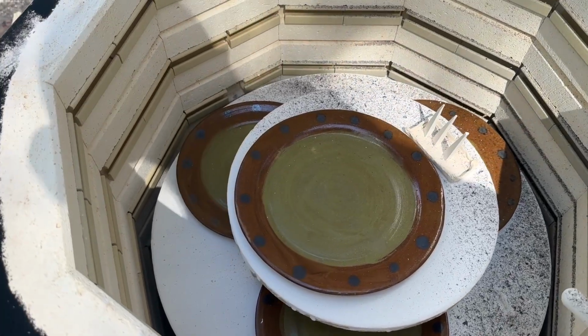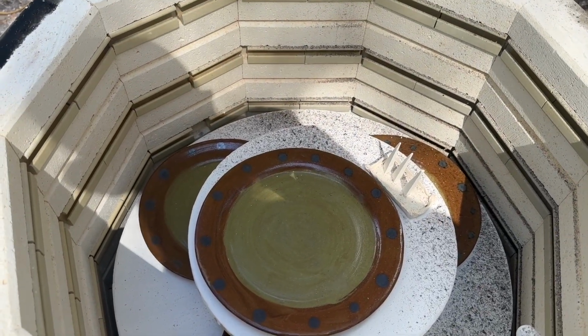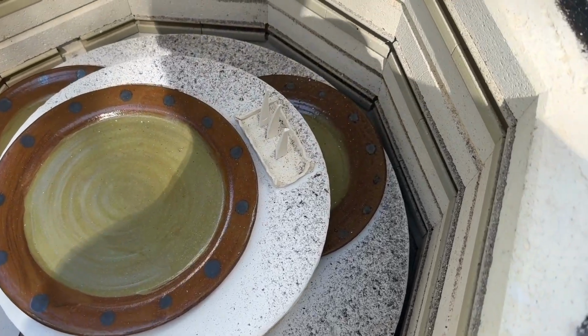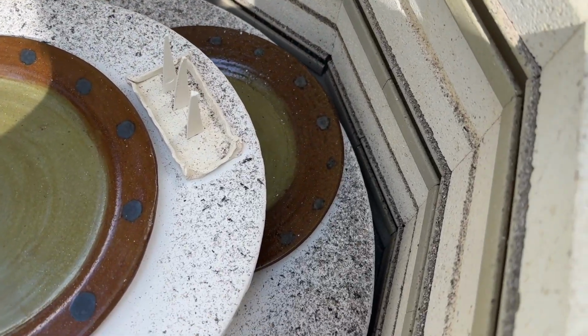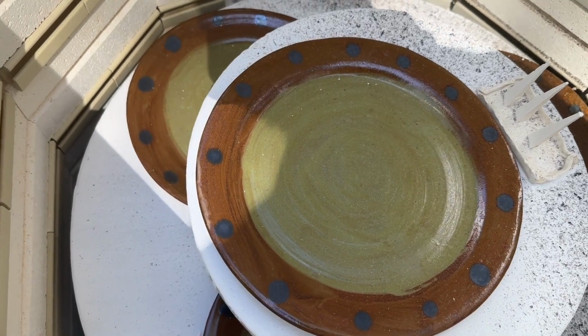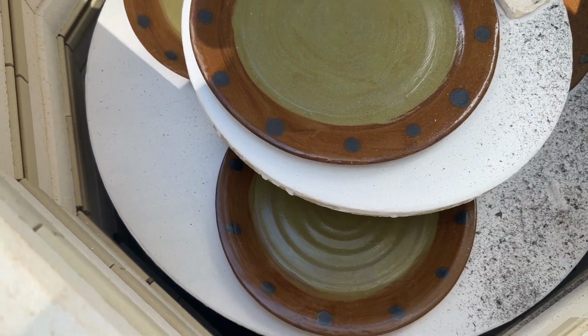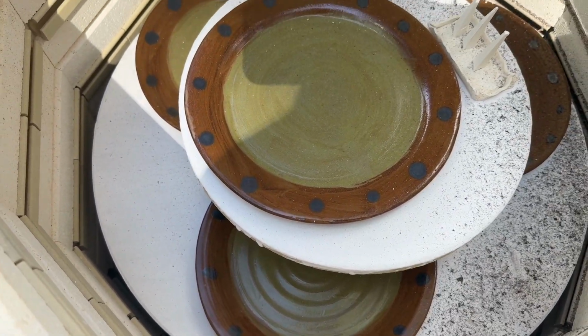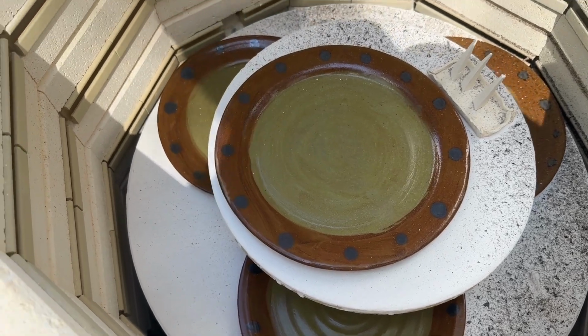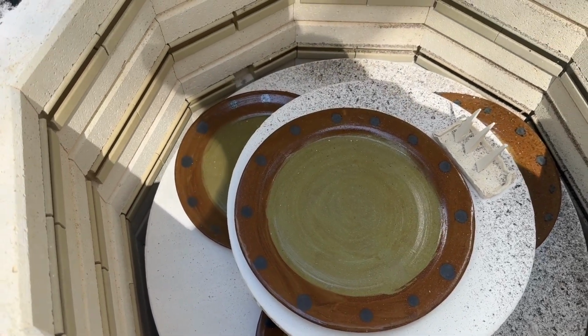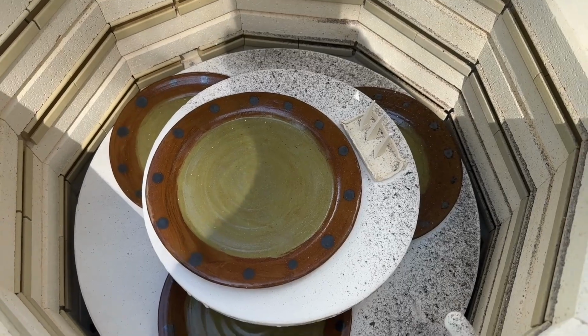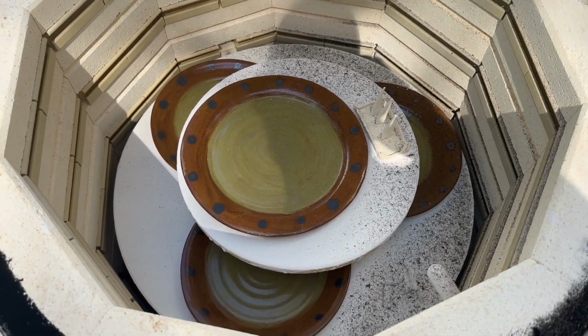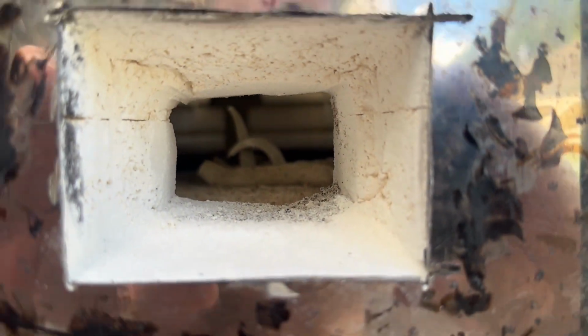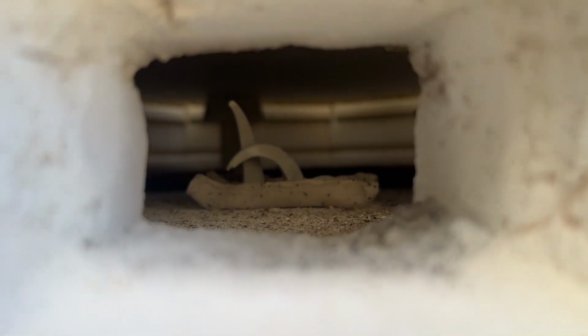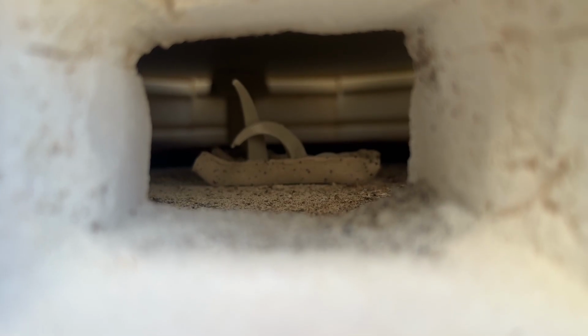So here's the kiln after I fired it. We can see that top didn't fire to cone 5, so cones 5, 6, and 7 are all standing upright. Although somehow the glaze ended up melting. There is a little bit of wood ash on that plate to the right on that second to top shelf. So, not a bad first try. You can see how we can see those cones. That one was perfect. That's a good cone 6 firing on that mid-level shelf.